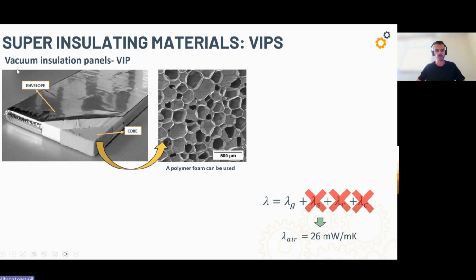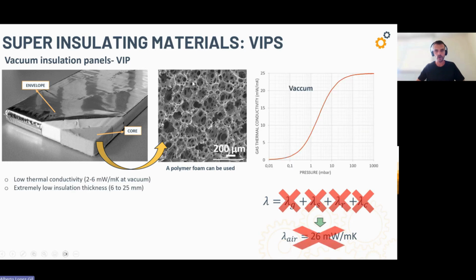This is in essence a vacuum insulation panel. It's a sandwich material in which we have a core and an aluminum layer on top. So in essence, we have a sandwich structure. And as a core of the vacuum insulation panel, we can have nanometric silica particles, which are compacted. This is a typical product in the core of the vacuum insulation panel, but we can also have a foam, which in this case is not a closed cell foam, as we said before for conventional thermal insulation application. This is an open cell foam because we need to evacuate the air, the gas inside the foam using vacuum.